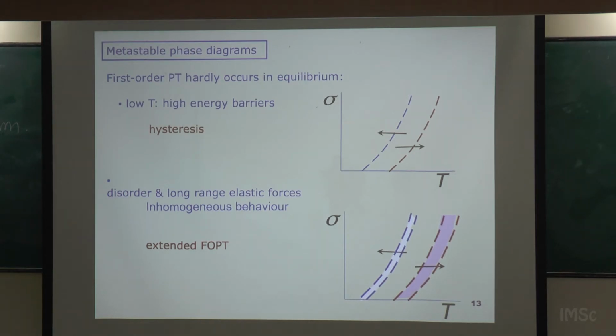What happens in reality? In reality, you go to the phase diagram, you go to the handbooks of different materials that have phase transitions, and you see that this line, this famous transition line, is not a line. It's at least two lines, because these systems, typically first order phase transitions, exhibit what we call hysteresis. So you have one line like this.